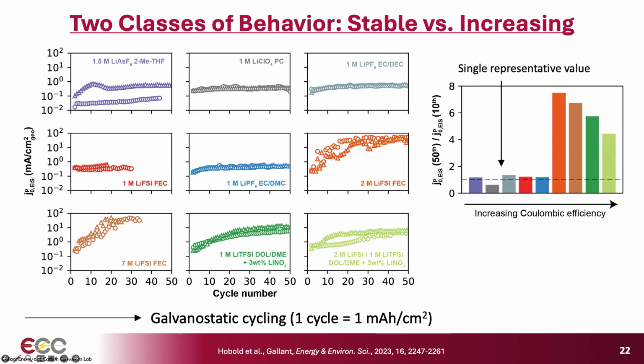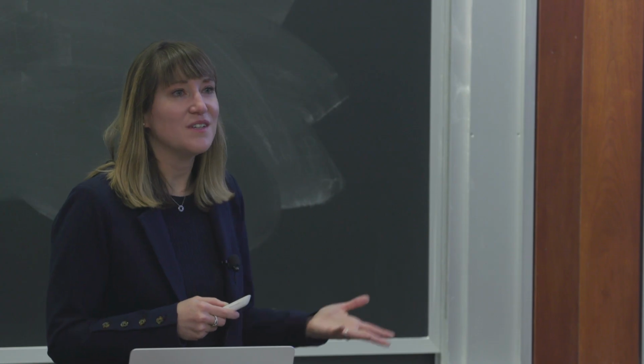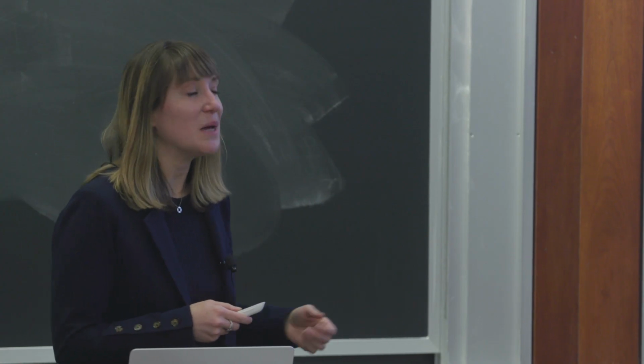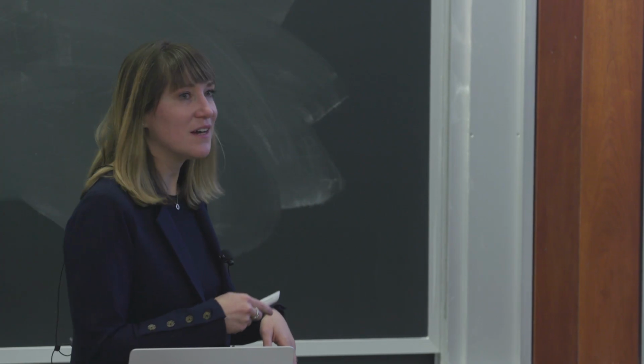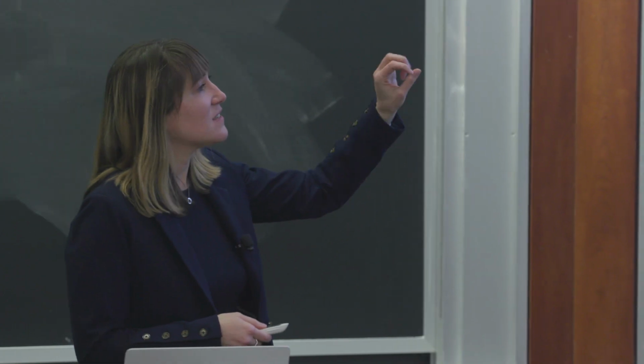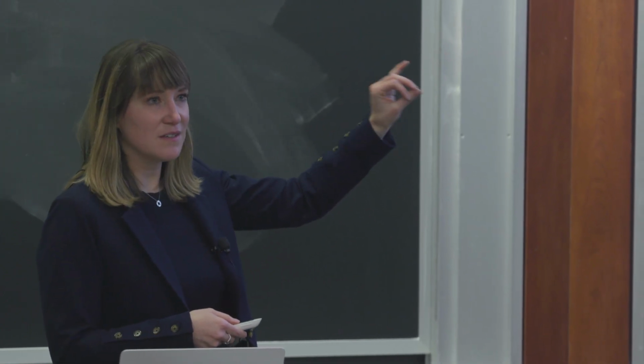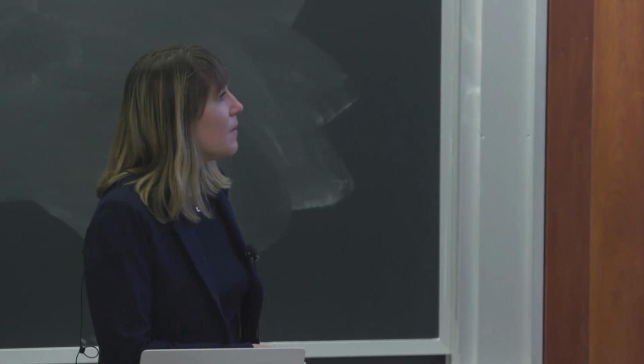through that SEI. But there are a couple of other examples, or counterexamples, and particularly for the high Coulombic efficiency systems, we saw that the J naught value continued to increase with cycling. So it was more like a dynamic parameter. Eventually, they do stabilize if you cycle beyond what we've shown here. We really wanted to understand why and what that was telling us, but clearly we can't just assign a single representative value to these cases. It's going to be dependent on the conditions.